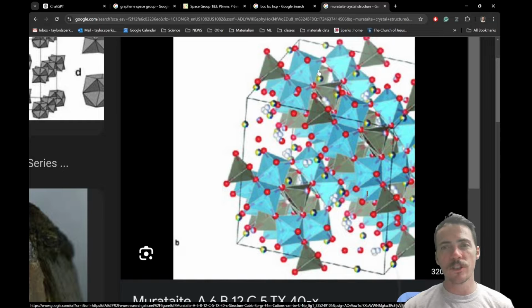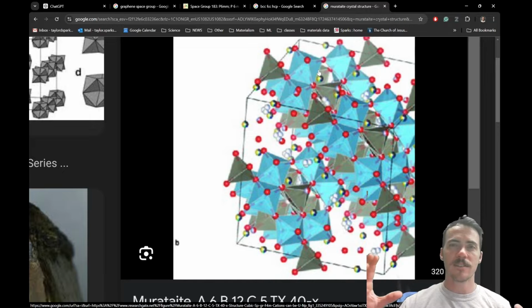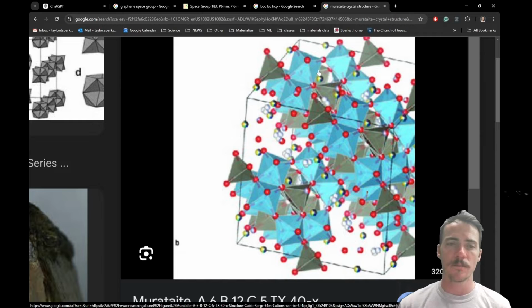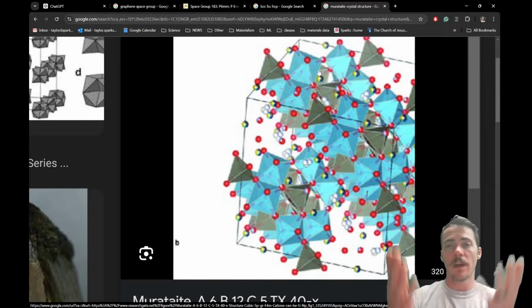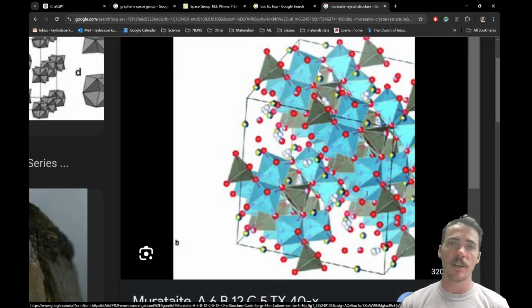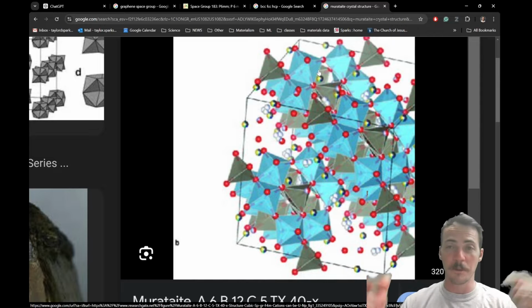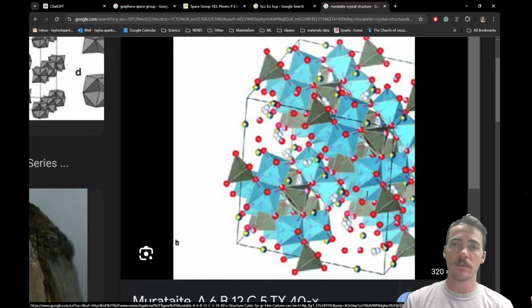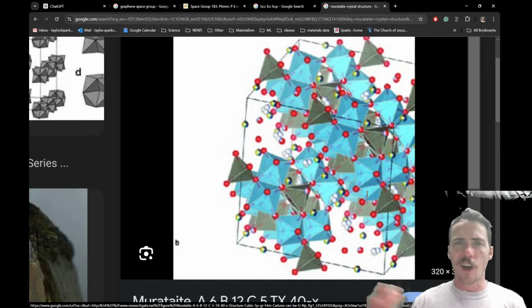It's actually really useful to use symmetry to describe things so that we know what in this overall picture of the unit cell has the same local environment. Because usually that's what's going to dictate the properties and help us understand the structure. It's also a much simpler way to describe it. Here we have hundreds of atoms, but if you think about it in terms of symmetry, there's a few unique positions, and then when you apply the different symmetry operators, which we're going to learn about in these videos, it produces all the rest of those atoms. So instead of having to keep track of every single one of those, saying X, Y, Z coordinates, you find an atom here, and you find an atom here. Instead, you say, here's the basis of a few atoms, and if we apply symmetry, it gives us all the rest.